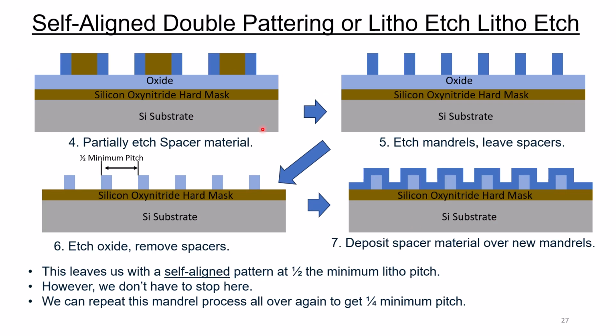Now this is the same diagram we had before, so we're starting at this diagram. Now we come in and we actually strip the mandrel, so all it does is it leaves the spacers behind in this 5th step here. Now we use the spacers as a mask to etch the oxide, number 6 here, and we remove the spacers. So now we have the oxide defined, and it's at half pitch, and it's all been self-aligned.